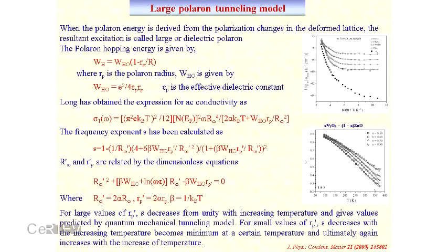For other models, there is a large polaron, then we can see the frequency exponent is related in a complicated way, and here is the conductivity, and we have shown here the result of our analysis using this model. You can see this is the exponent and this is the conductivity as a function of temperature. We have fitted this conductivity and the frequency exponent simultaneously with different values of the parameters. These parameters are the localization length and the polaron radius. We calculated these two parameters from this fitting, and we can see that there is a perfect agreement between theory and experiment for conductivity as well as the frequency exponent. So this model is one of the best models to describe the AC electronic conductivity in semiconducting glasses.